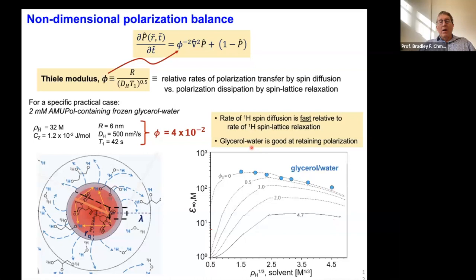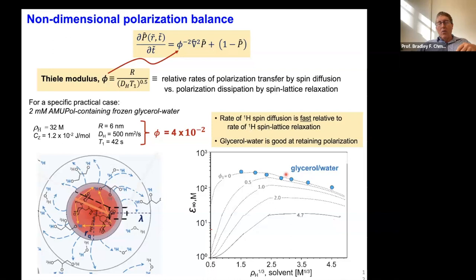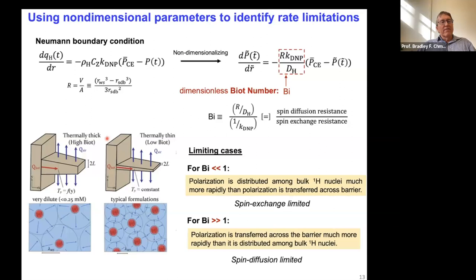If you change parameters by increasing the proton density in the solvent, you'll see that this Thiele modulus will be reduced and you'll end up reducing your enhancement. So we can essentially predict the enhancement. If you want to use a different level of deuteration, different glycerol-water ratio, or another solvent like tetrachloroethane or dichlorobenzene, you can do this in a similar way, because all the parameters are known, and you can easily figure out where you want to be.